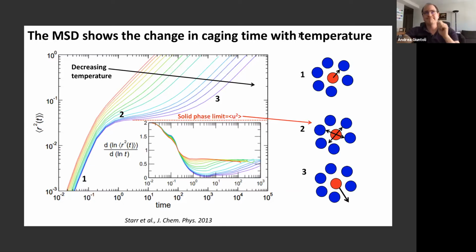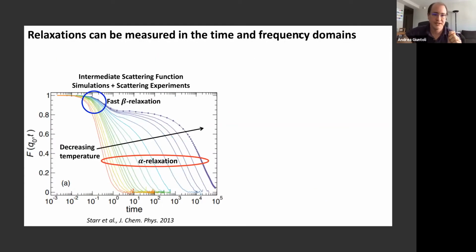But okay, now let's see, how do we measure exactly this relaxation time? There are two main ways. One is to observe the intermediate scattering function. That is a function that measures the decorrelation of some scale, in this case, the scale of the cage, over time. So when this function is going down, it means that the structure is decorrelating. Here, typically you'll see two different relaxations. The first one, which is always around 1 picosecond, is the fast beta relaxation, and it's related to this rattling motion inside the cage. And then, varying with time depending on your conditions, you'll see the alpha relaxation, the breakdown of the cage.